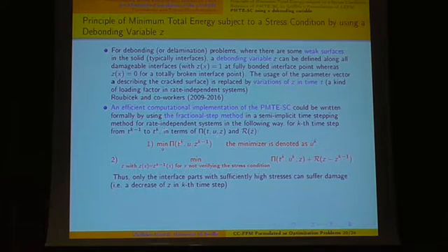It means we can minimize the potential energy, minimizing with respect to the displacement field. This minimizer is, let's say, in the time step u_k. And in the second fractional step, we minimize the sum of the potential and dissipated energy with respect to zeta, but we keep zeta fixed for those points x in the interface which don't verify the stress condition. It means actually we minimize zeta only on the part of the interface where high stresses are applied.